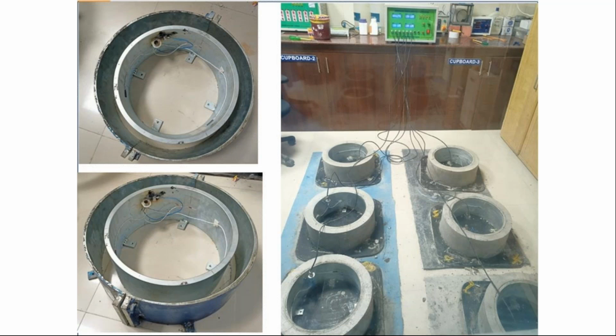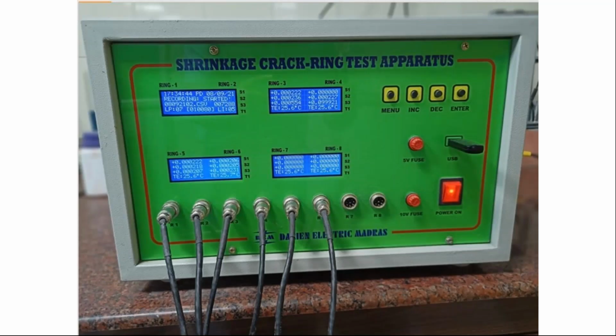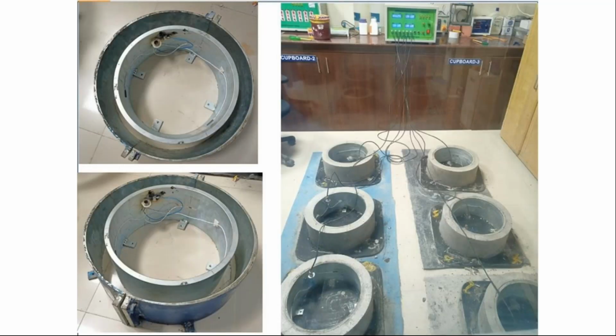Now this is something which we have seen again, a test which we call the shrinkage crack test, the ring test, with the shrinkage crack ring test apparatus, where the probability of cracks in concrete can be measured. The testing is to identify the potential cracking risk of concrete and mortar mixtures. That is what it is being used for. It consists of a steel ring, which acts as a restraining support around which concrete is poured. When drying, concrete tends to shrink and the movement is restrained by the steel ring. So it generates tensile stress in concrete.